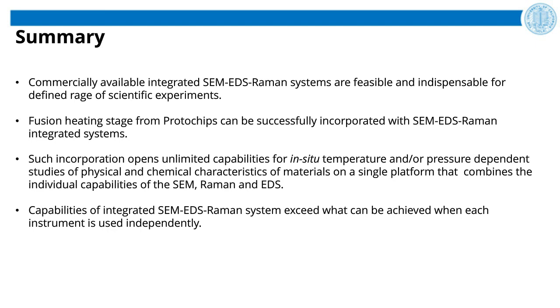there is no problem. It's like any sample, when you put it in the SEM, you care about how clean it is, and you try not to contaminate it. So contamination can be a serious issue. You simply do not measure the signal from your material; you measure the signal from the contaminant. But generally, it can be handled nicely, especially in SEM.